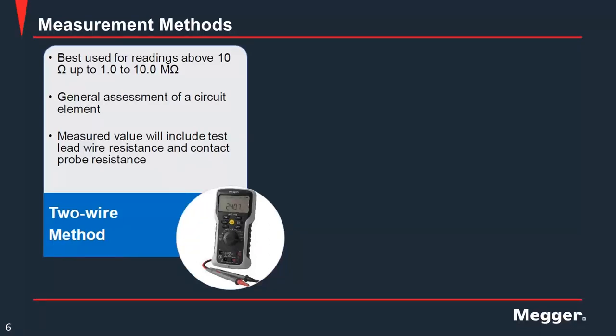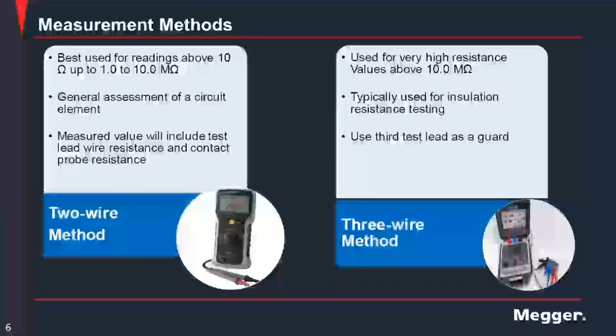So the next method, if you see it on the right screen, is the three-wire method. This typically is used for very high resistance values that will be measured in megaohms. And this method is used for what we call insulation resistance testing. Mostly we use this for insulation resistance testing. Although insulation testing can be performed with two wires, it's very important to understand to use the third lead, which we call a guard lead. So for different types of surface contamination, that contamination can be guarded and excluded from your resistance measurement.